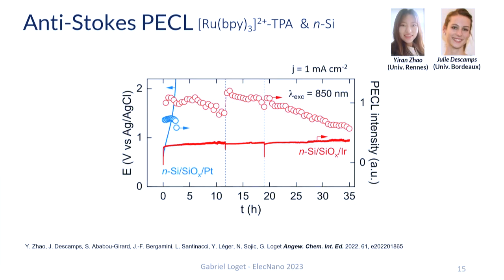So now, how long can this work? Here you can see some stability tests which are done galvanostatically. So we apply a constant photocurrent density. The red data is the data obtained for the iridium thin film. The blue data is the data obtained for the platinum thin film. The lines are the potential of this working electrode, and the disks are the normalized PECL intensity.